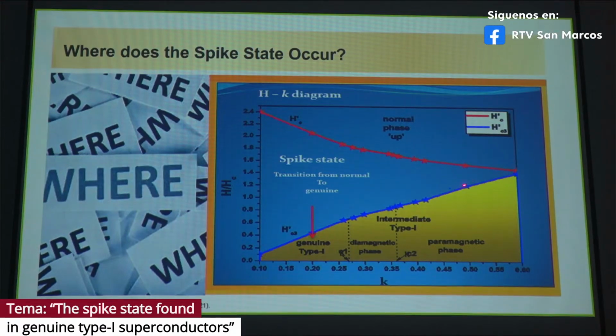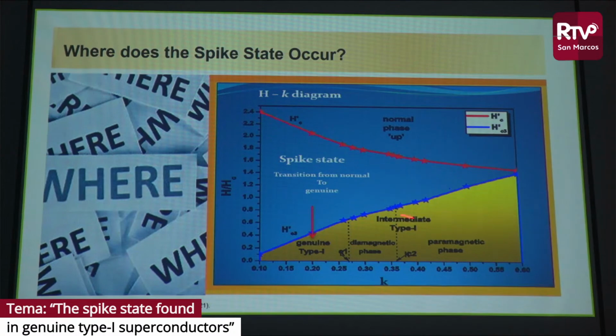But when you cross this blue line, it goes to a superconductor state, and you can see that it has different critical fields. This critical field destroys the superconductivity, and this critical field creates the superconducting state again. Okay, we can see the yellow region, so you can take other Ginzburg-Landau constants here and analyze the magnetization curves, and with this we can divide this yellow region into many regions.